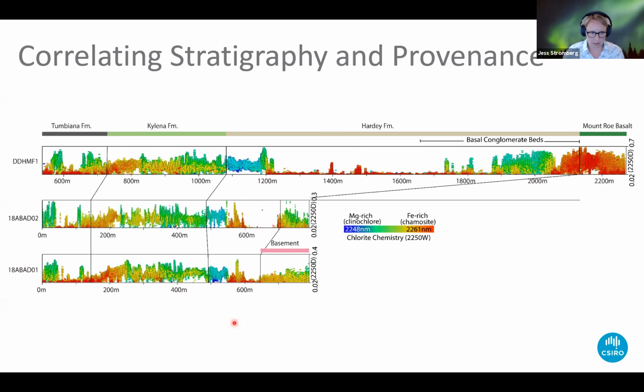And so if you want to get a little fancier and start looking at scalars, this is one of the more commonly used scalars looking at chlorite abundance in chemistry. So the 2250 nanometer feature is plotted, the depth of that feature is on the Y, and then the color is the position of that feature. So it tells you about the chemistry of the chlorites. And the thing that pops out to me is this unit right here, just below the Kylena contact. So that's that section that I mentioned. It's difficult to view that contact just from the raw data, but if you look at this, there's clearly something going on where this chlorite is very different from that. It's a more magnesium-rich chlorite, and so that's a really clear stratigraphic marker that I think is quite interesting.